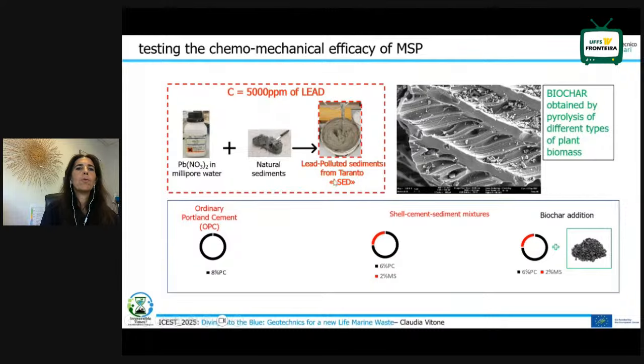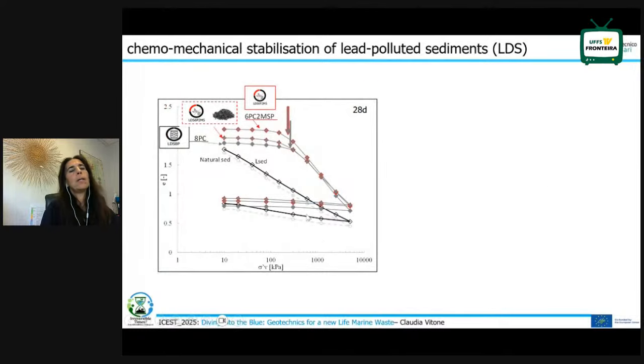So now we will just focus on the Portland cement, and just a few words about the other cement. These are, again, oedometer tests in the void ratio versus vertical effective stress plot, so one-dimensional compression. This is the natural sediment here, dashed line in gray. The black line is the lead polluted sediment. As you can see here, we have quite similar behavior for the control mixture, the mixture with just shells and cement, and the mixture when we have added also the biochar. So essentially we have a pre-yield and a post-yield, so the mechanical stabilization is still working.